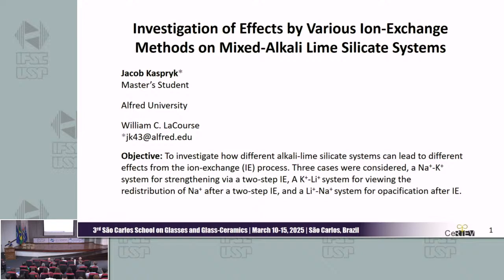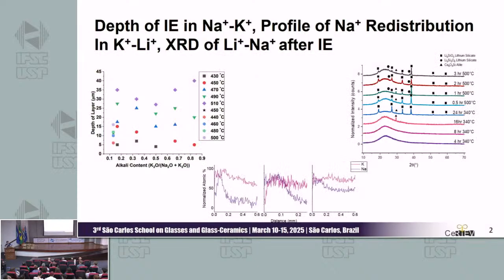Three cases we considered: a sodium-potassium exchange system for strengthening the glass via a two-step ion exchange, a potassium-lithium system for viewing the redistribution of sodium ions after a two-step ion exchange, and a third system, a lithium-sodium system, for how you can actually cause opacification through ion exchange. These are my three main graphs. The first graph shows the depth of exchange from my two-step ion exchange. The middle graph is about the sodium redistribution in the glass. The third graph has some XRD about opacifying the glass after ion exchange.